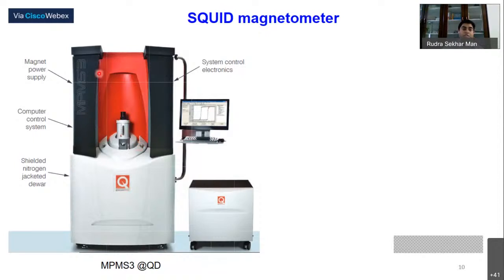And how they do it, a typical magnetometer, which is commercially available, you can see the principle inside. So this is also a cryostat. Outside it is isolated, and it's a magnetic system. I think one demo picture is given. Like if you have a ferromagnet, you can see how the hysteresis is measured. And that is Quantum Design, the company that sells this very high-end equipment, and you can do precise measurements. Inside the device, you can have a magnetic field of the order of I think 5 to 7 Tesla, or you can go to as low a temperature as you can, like if there is some provision, you can go to the millikelvin temperature range.